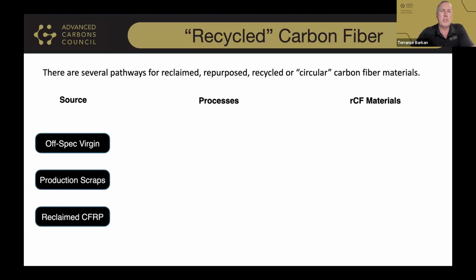One is the source of these reclaimed fiber materials. There is a significant stream of material that's coming directly from virgin carbon fiber producers for material that is off spec. Now, this just might be a box of spaghetti, or this might be material that's actually on spools, but it didn't meet spec, and therefore it can't be used in their normal sales process, and it gets diverted into the reclaimed, recycled sector. Then you've got production scraps from facilities making composite parts, and these are the offcuts from the patterns that are not usable. Those are production scraps. And then we have material, for example, end of life windmill spars, where the materials are being reclaimed.